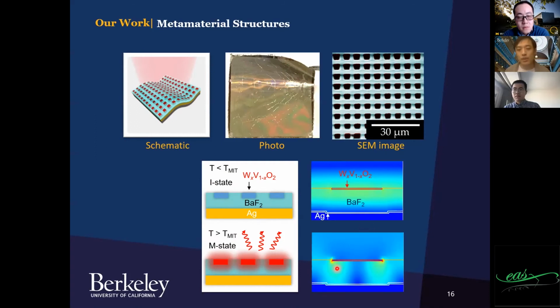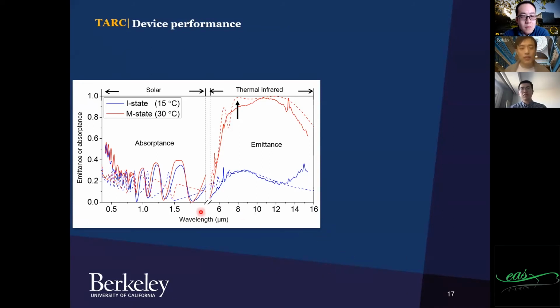And this comes to the simulation. You can see at high temperatures, strong plasmonic effects appear, so that the emittance is increased. So this is the device performance characterized by spectrometer and FTIR. So in this picture, the blue curve and red curve are the I state, low temperature state, and M state, high temperature state, respectively, while the solid curves and the dashed curves are the experimental data and the simulation data. So in the visible to NIR range, the absorbance of solar light is almost static, regardless of the temperature. Meanwhile, its thermal emittance can be switched on and off according to the temperature.